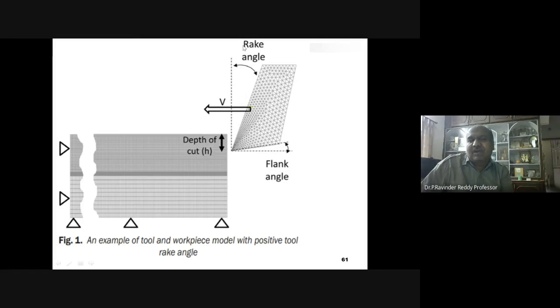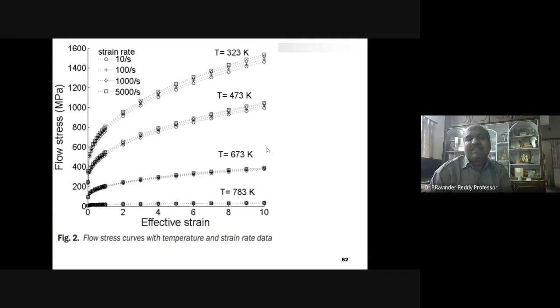And some of the analysis we performed with changing the rake angle. So when you change the rake angle, again remesh it, again you should have a contact, then you have to have the models. And we can measure the wear also, flank wear, right, and nose wear and all. So with such a model at different strain rates, we can calculate the flow stress values at different temperatures. When you plot flow stress versus effective strain at different temperatures, we can see at different strains, higher strains and lower strains. For 10 to 5000, at the higher temperatures, the strain rates almost don't affect anything. But at lower temperatures, there is going to be variation among the strain rates. So that's the observation you can make.